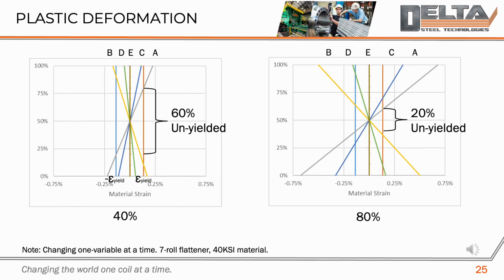On this slide, we're comparing 2 charts that illustrate the effect of plastic deformation on the material as it progresses through a 7-roll leveler. These charts highlight the relationship between the percentage of deformation and the amount of unyielded material. The first chart shows a material that has experienced 40% deformation. With this lower level of deformation, a significant 60% of the material remains in the unyielded zone, meaning the elastic zone is still large. This leaves much of the material's internal stresses unresolved, which limits the improvement in flatness.